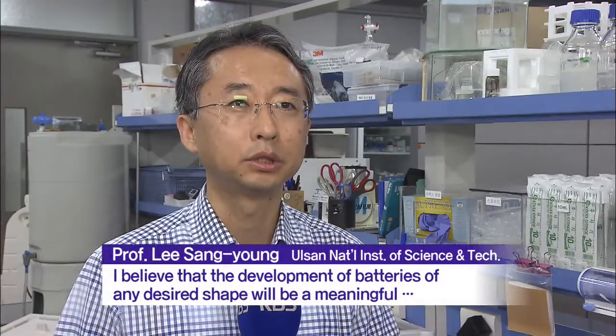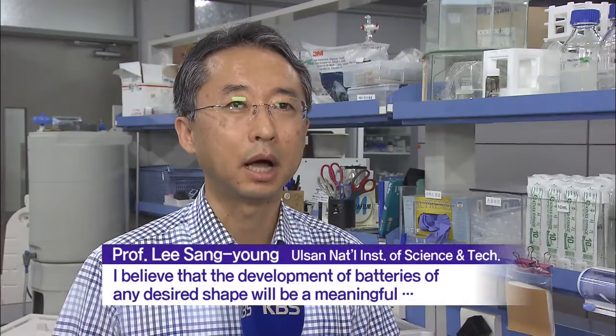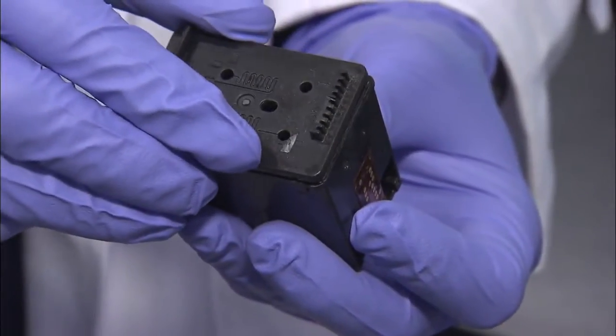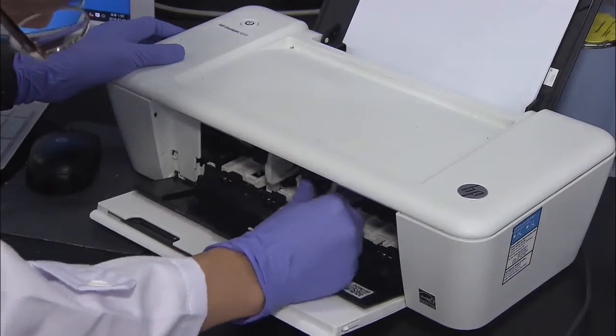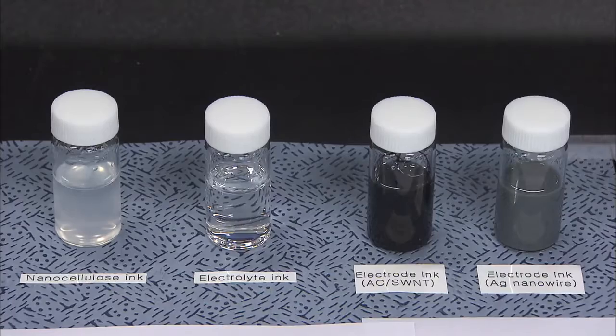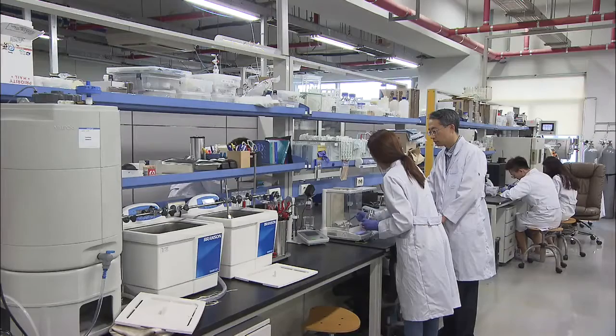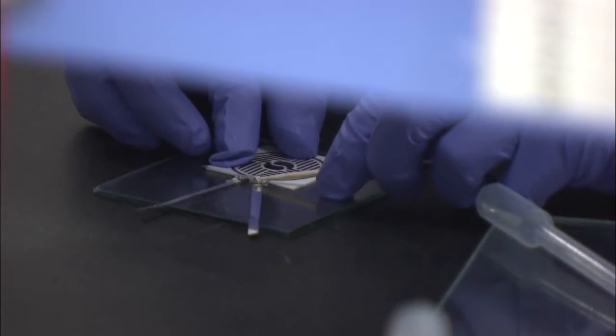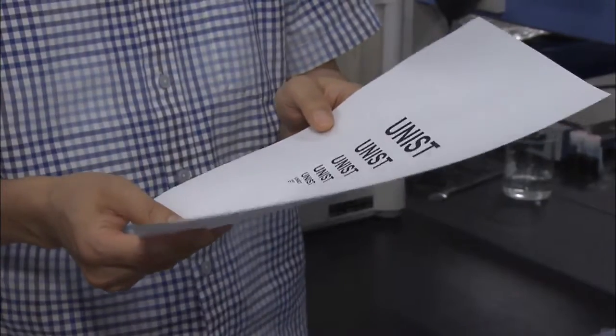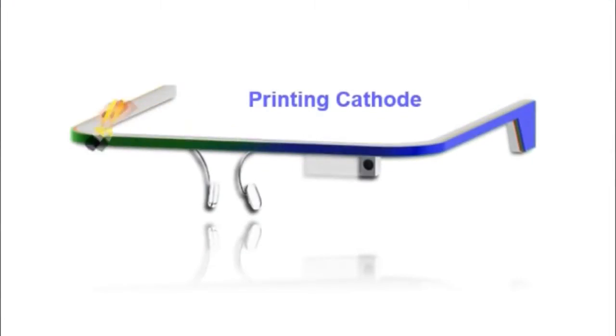The researchers adjusted the viscosity so that the battery can be used in regular printers as well and use nano-sized cellulose to prevent smudges on paper. The new battery maintains its capacity even after being discharged and recharged over 10,000 times and even at 150 degrees Celsius.